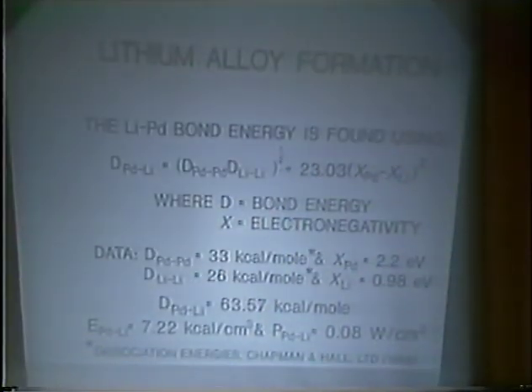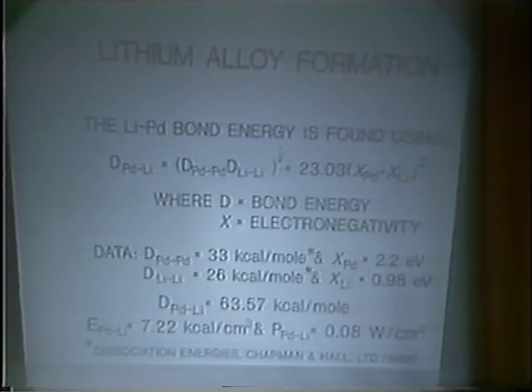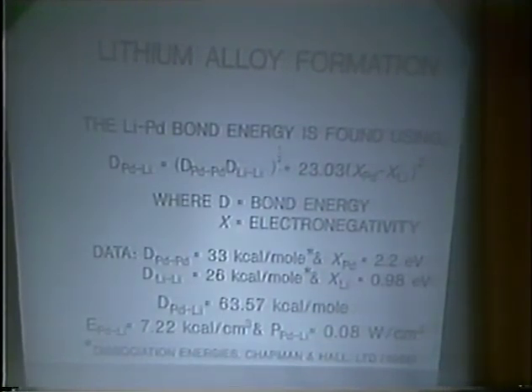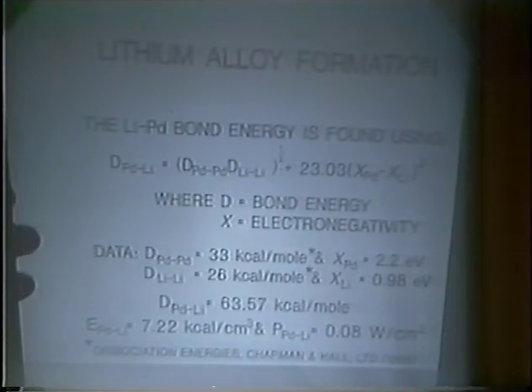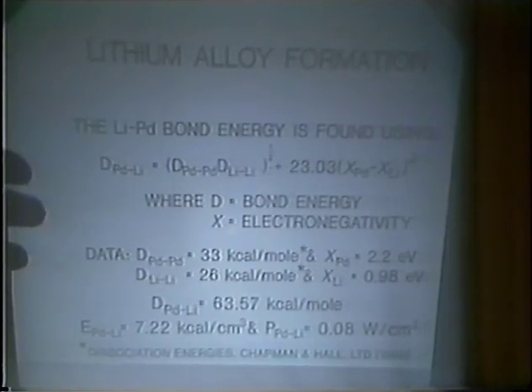So I've gone the whole hog, and I've assumed that the whole darned electrode is a lithium-palladium alloy after 100 hours, which is an extremely unlikely but conservative assumption. And then I've taken various bond strengths from a book on bond strengths, and I've come out with palladium-lithium bond strength, and please don't argue that one with me and tell me it's really 52 or something, because it doesn't make any difference. It can be halved or doubled. It's all going to be much less than 0.1 watts per cc if you take it over 100 hours.